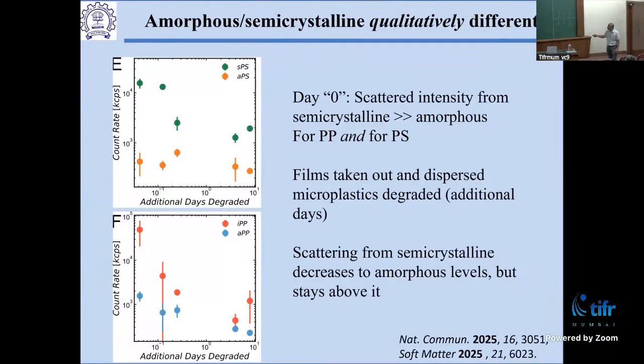So notice that these two things which give you much less scattering are the amorphous polymers that do not crystallize, while the ones that do scatter a lot, that give you a lot of particles, are the crystalline polymers, right? Why is that the case? This was a non-intuitive kind of a finding, and so we were very surprised when we saw that, right?